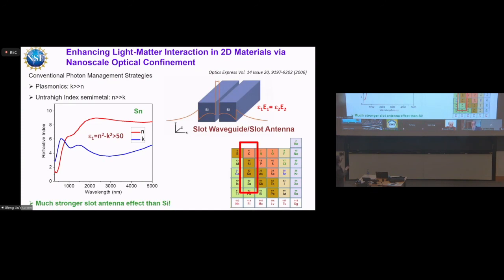So essentially you can utilize the slot between two high index materials to confine the light into a very small slot. And that's due to the continuity requirement at the interface from Maxwell's equations. Electric displacement has to be continuous in the normal direction if there's no surface charge accumulation. So that means if you have a low dielectric constant, then your field at the interface will have to be high. If you put two of those interfaces really close to each other, you get a strong field enhancement in the slot. Of course, the best thing you can do is to insert those graphene layers into the slot. You get a really strong enhancement in absorption, but that actually turns out to be more difficult to fabricate.